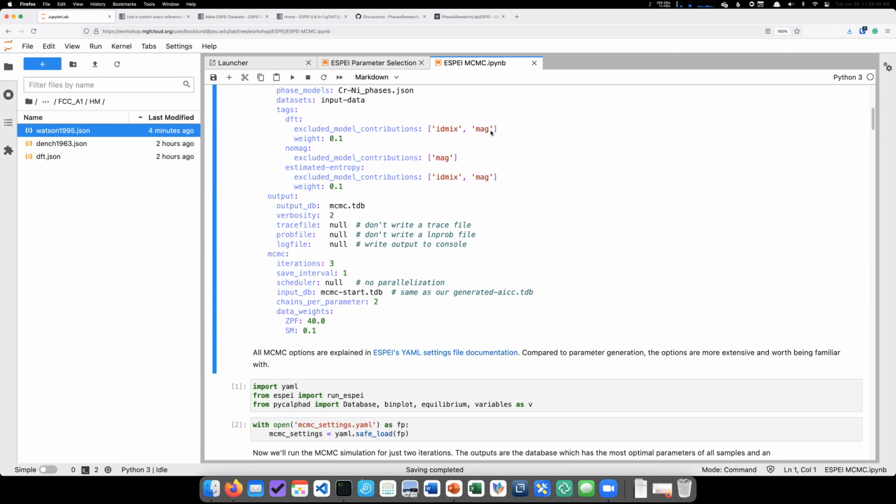So what we did for our estimates, and I admit it's extremely crude, but it's the best we can do without further first principles calculations, is just use the ratio between magnetic moment and Curie temperature for the stable experimental magnetism that we know, and then use the DFT magnetic moment to estimate a Curie temperature.